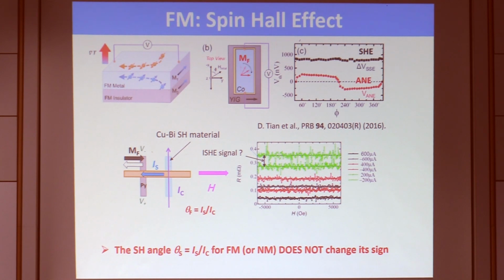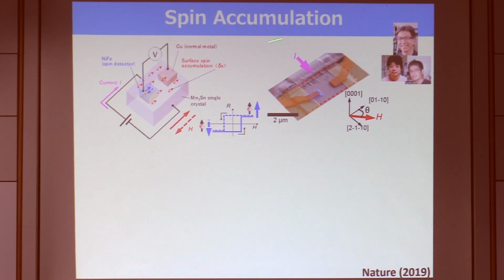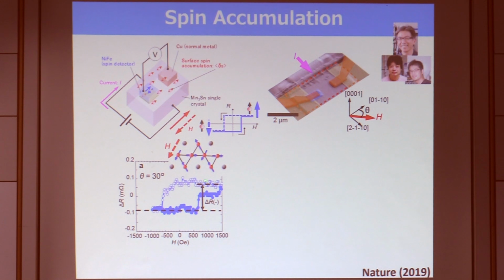We also checked the spin Hall effect by using spin accumulation, in collaboration with Professor Otani's group. They made this type of device. Manganese tin, a bulk FIB-made device, and they put a spin detector, permalloy, on top, and this is the probe. They monitor the voltage as a function of the field, at which the permalloy magnetization reverses. If we see this type of rotation, we find that spin accumulation on the surface does exist. And in fact, we find a clear hysteresis indicating there is indeed surface spin accumulation.